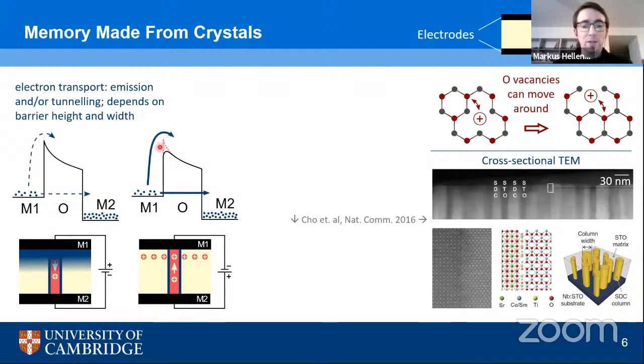as I indicated here. And then with the ingredient that I pointed out before, we can change the height of the barrier by moving around the oxygen vacancies in the material. So if the barrier is lower, more electrons can get over it to the other side. If we reverse the voltages and instead apply a negative voltage to M2, the second electrode, then the positive oxygen vacancies will be drawn back into the material and the barrier assumes its previous state. So we can switch back and forth between these two states.